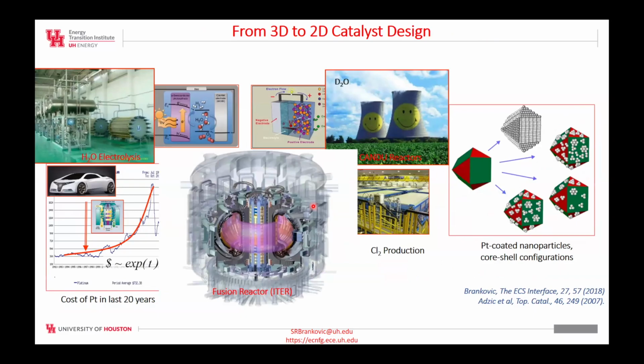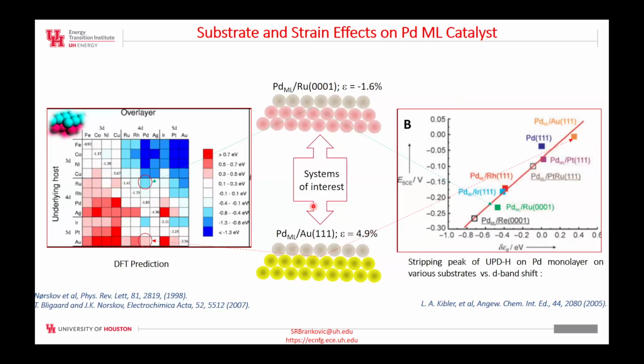And as I say, since we already consider electrolyzers for production of the hydrogen, therefore, as a side product, which probably would cost more than the produced hydrogen, would be ultra pure or heavy water, or eventually deuterium. So the concept that we propose, or actually demonstrate here, is based on a monolayer catalyst, which has an epitaxial relation with the substrate.